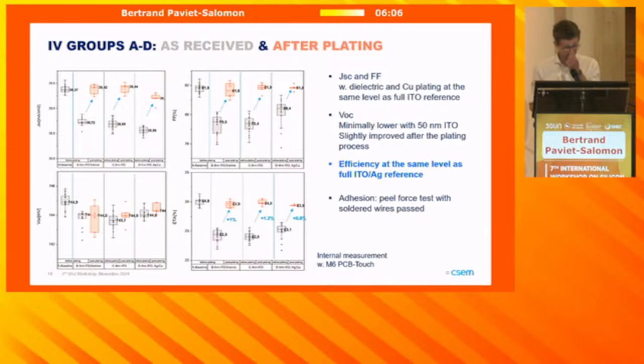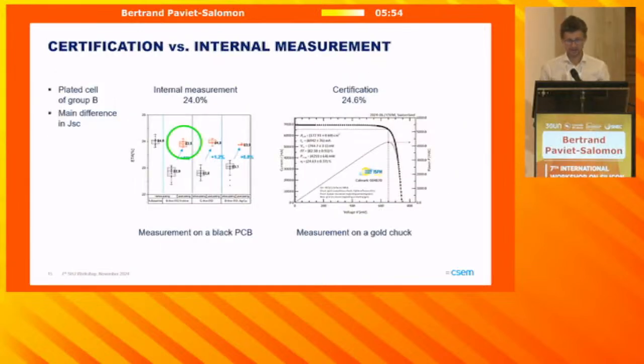So overall, efficiency-wise, all those groups with plating perform very similar to the reference, which, I recall again, was a reference with a full ITO thickness and a full silver printing. We selected some of the best devices of those groups and sent them to ISFH for certification. The best one came to be a 24.6% device, which we were, of course, very pleased with.